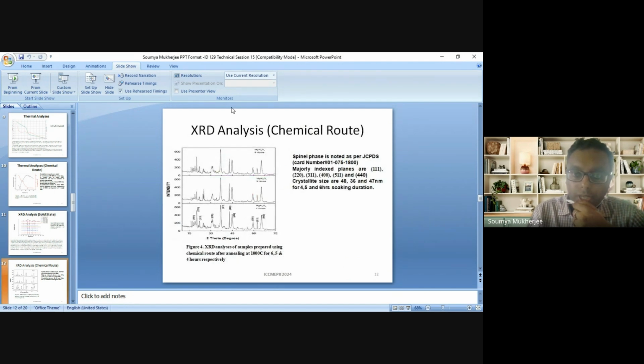For the chemical route, we have increased the temperature, although the initiation of crystallization is around 500, to avoid any unwanted phase since we are utilizing chemical solutions. We have indexed the peaks as per the JCPDS card number, and we carried out the heat treatment at 1000 for 4, 5 and 6 hours, and we are getting spinel. The crystal sizes are 48, 26 and 47 nanometers.